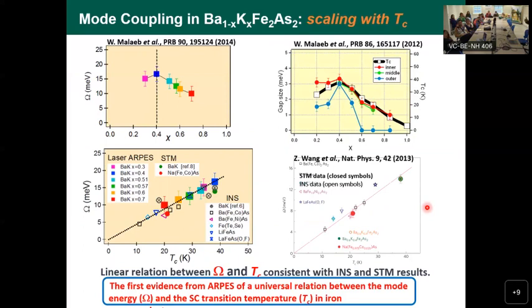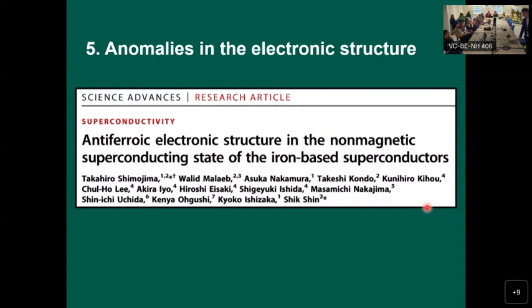So now we have an indication that there is a mode, even if we don't really understand this mode, but this mode is somehow related to superconductivity. So this is what I mean by deeper insight about the origin of the mechanism of superconductivity. So gradually, with the years, we gain a better understanding of this phenomenon.